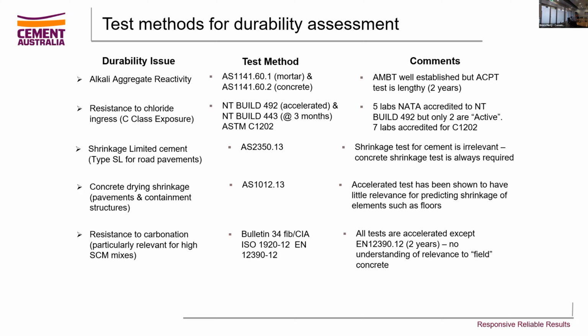The European one, the European 12390, is a long-term test, but we're still trying to work out what relevance a result in an accelerated carbonation test has in the field. And the evaluation of this test method is very much in its infancy. Here at Cement Australia, we are able to run this test method, and we can't work out really what is a good result and what is a not so good result. And there's no cross-referencing yet available to how concrete performs in the field. But this is being addressed. We're working with an academic institution to try and work out whether there is a link between accelerated testing and field experiences.